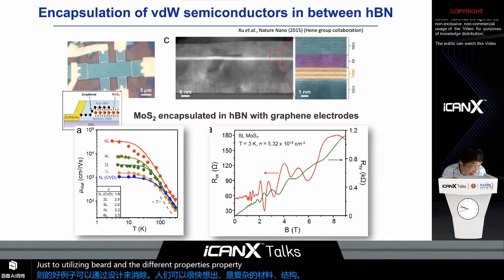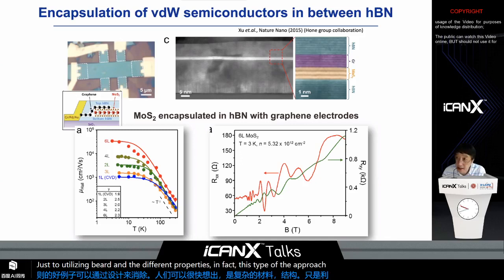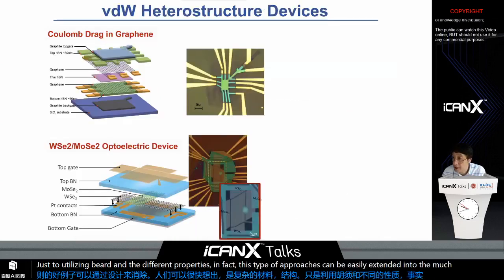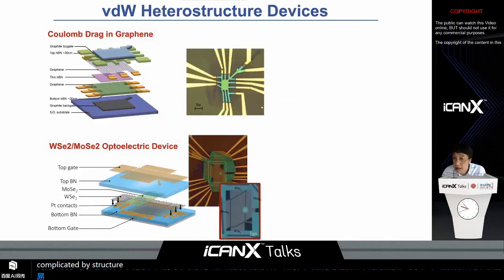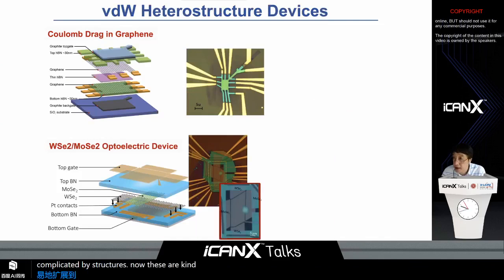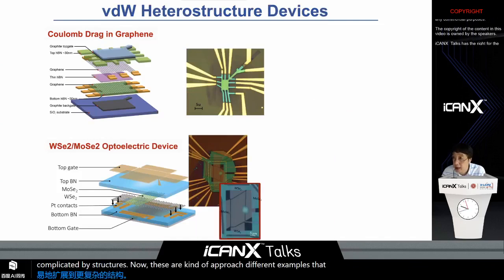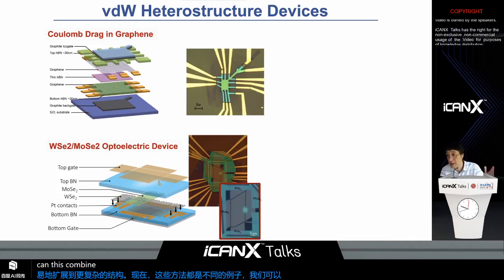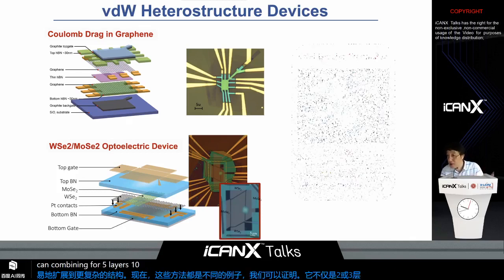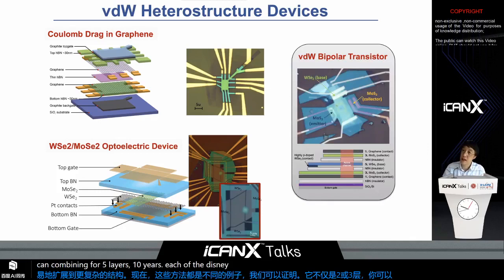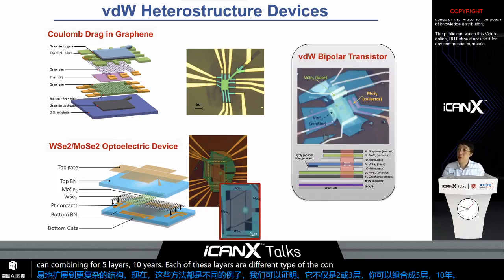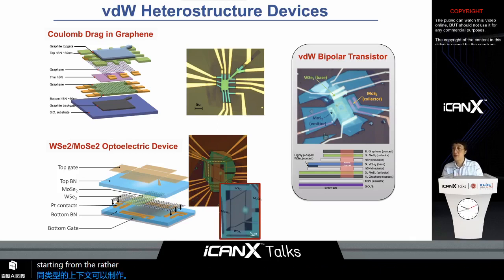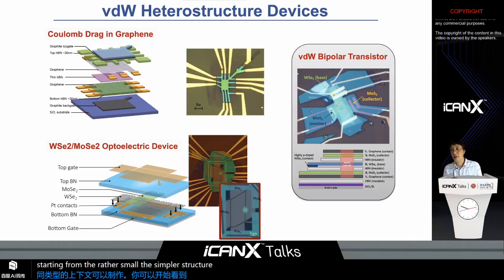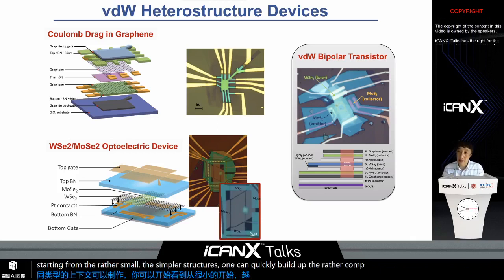In fact, this type of approach can be easily extended into much more complicated device structures. Now, these are a couple of different examples that one can demonstrate, not just two or three layers. You can combine four or five layers, 10 layers, and to each of these layers, again, different types of contacts can be made. You can start to see that starting from rather simple structures, one can quickly build up rather complicated structures just by design.